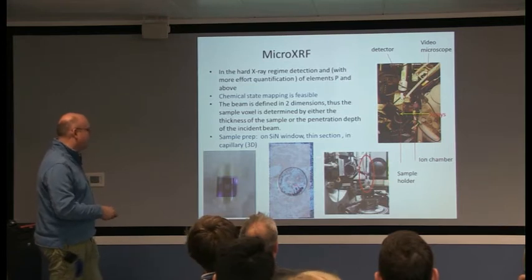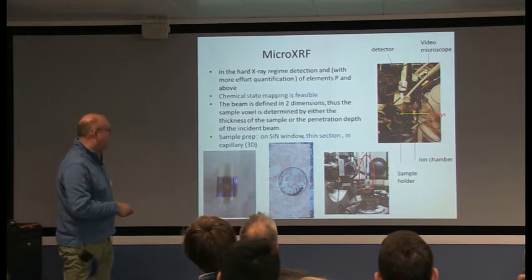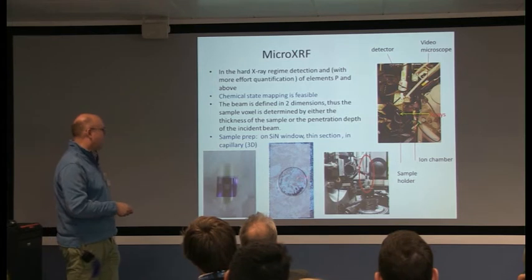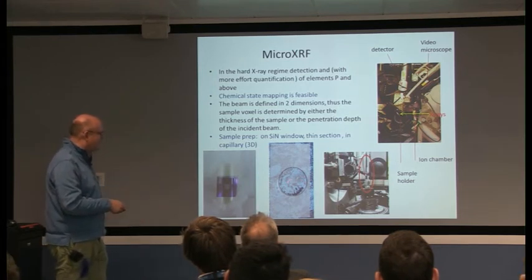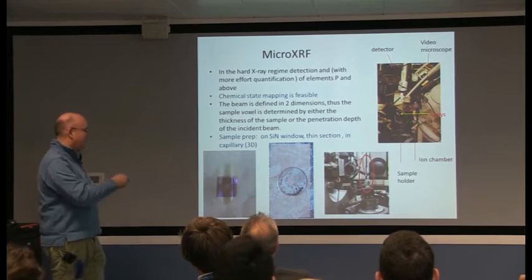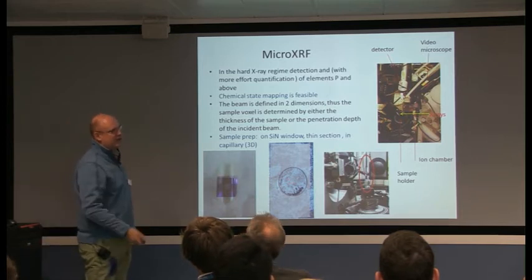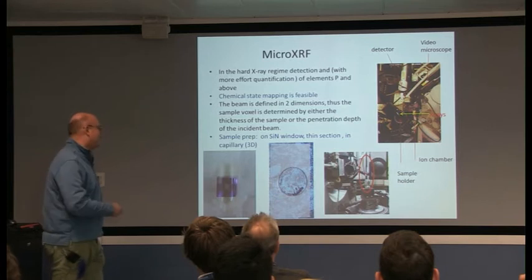Also, we look at thin sections. This is a thin section of some calcium carbonate worm granules which have been polished down, and actually this slide, though it's very unobvious from the photo, has a hole in the back of it, so the granule sits over a hole, which means we can do diffraction and XANES on it at the same time.